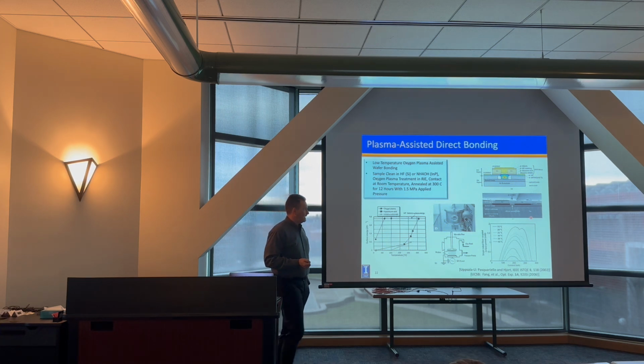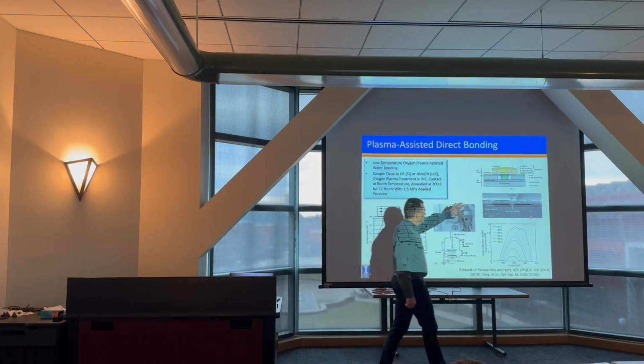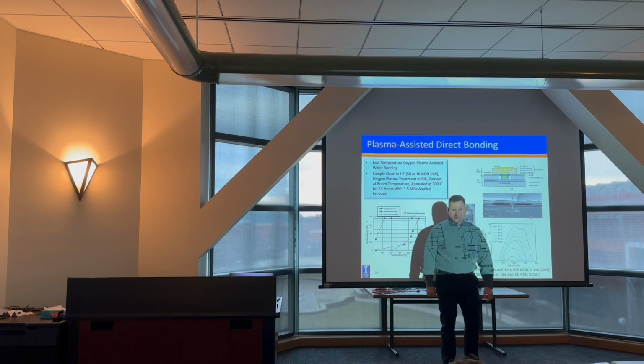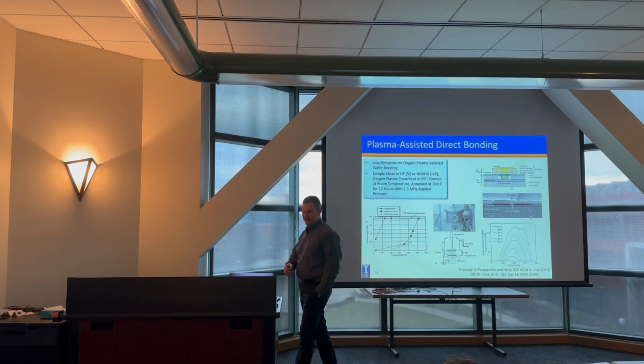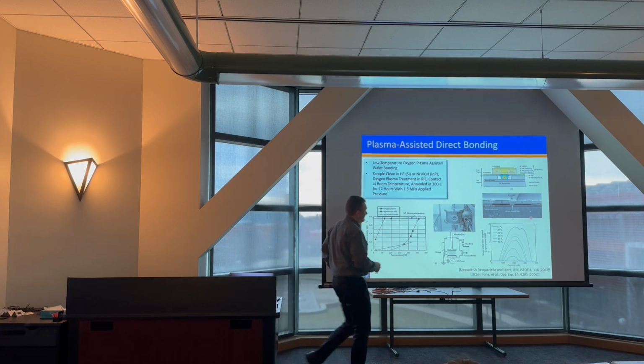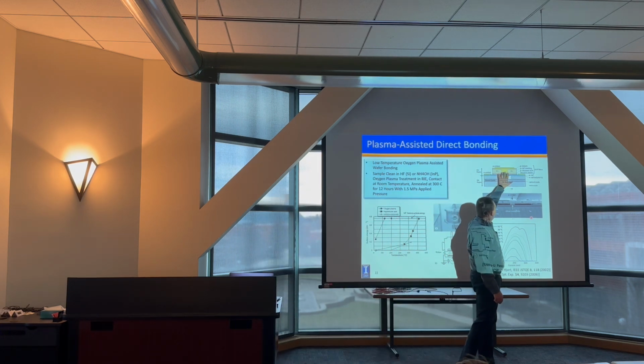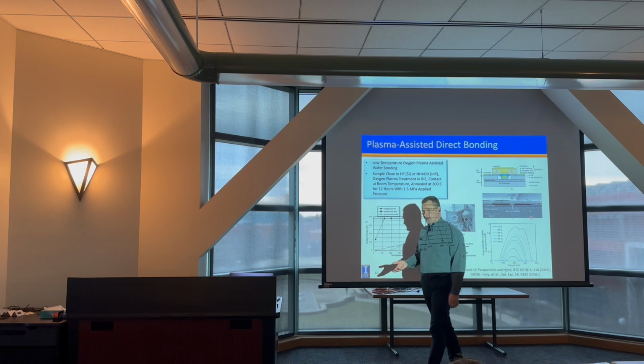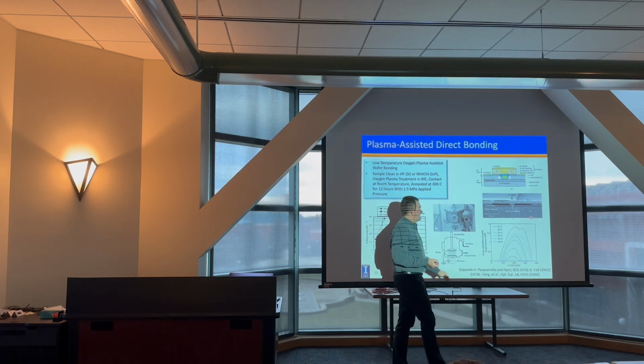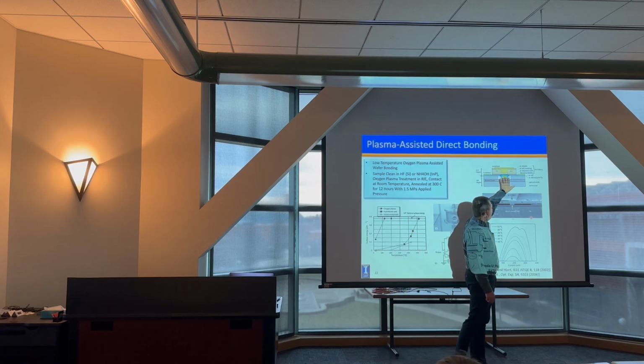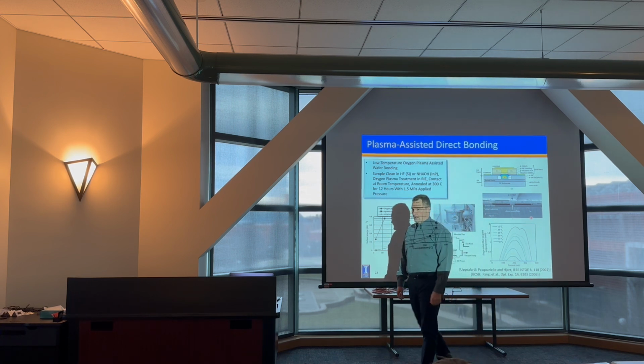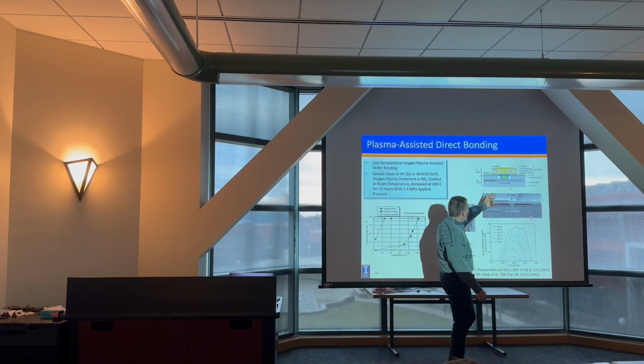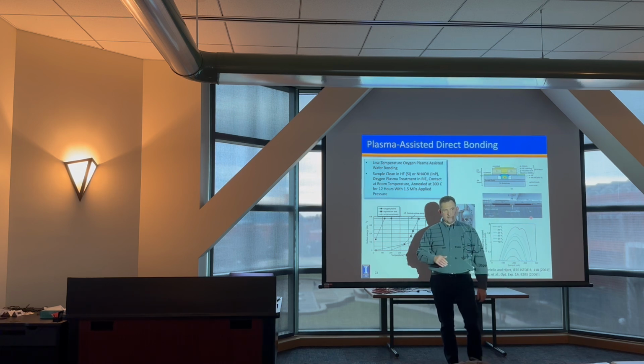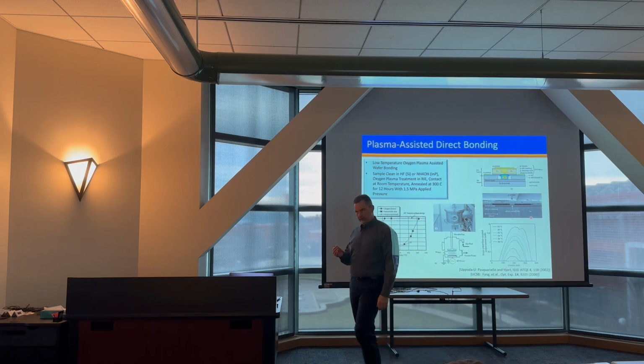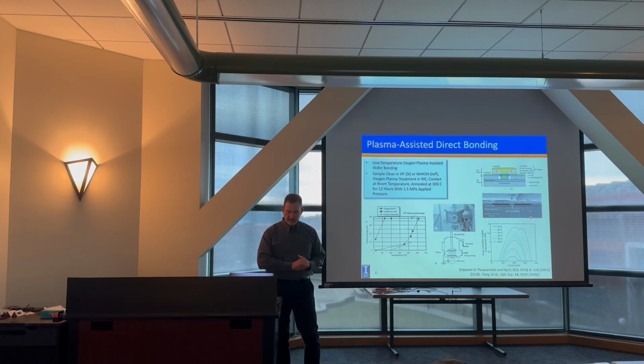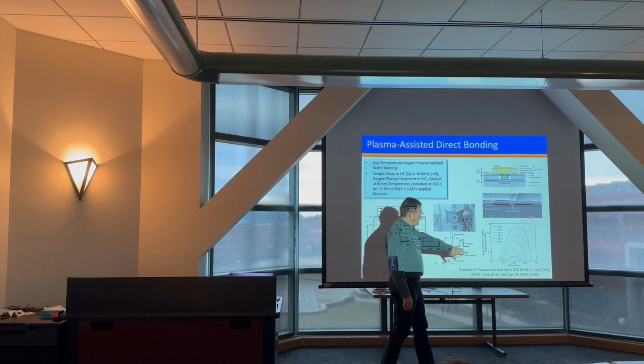Plasma-assisted wafer bonding has also been used, so this is what Bowers did. This figure probably showed up in 1 million publications. But basically what they did was take a gain region, a III-V gain region, using plasma activated low temperature bonding. They bonded that to a silicon waveguide, such that the mode was mostly present in the silicon waveguide, but had enough overlap with the gain region to allow the device to lase, and they were able to make lasers using this technique as well.